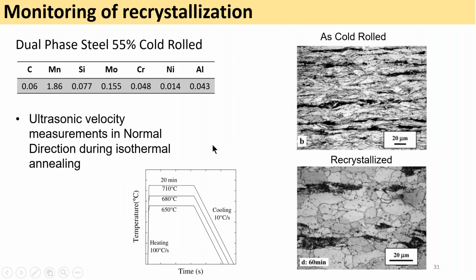So velocity, as I said, was used here to measure phase transformation, but it can also be used to measure recrystallization. This is the purpose of these slides, where we have a dual phase steel which is cold rolled. You can see here the microstructure of the as cold rolled sample, which consists of ferrite, pearlite, and bainite, and is elongated in the direction of rolling. After the recrystallization, we end up with a ferrite plus bainite microstructure in which the grains are equiaxed. This recrystallization has occurred during an isothermal holding at various conditions.